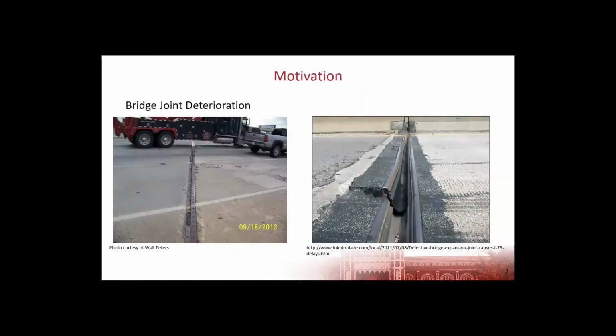So if we go to the next one here, think about the motivation behind the study that we're looking at, especially in Oklahoma. We have a lot of bridge deck joints that are in pretty bad shape. And here I've got a couple of pictures of some of those deck joints that are deteriorating, where we have some perforations through the sealant material within the deck. If you look at just Oklahoma, you line up all these joints end to end, we have somewhere in the neighborhood of about 50 miles of joints that are currently in need of repair and rehabilitation.